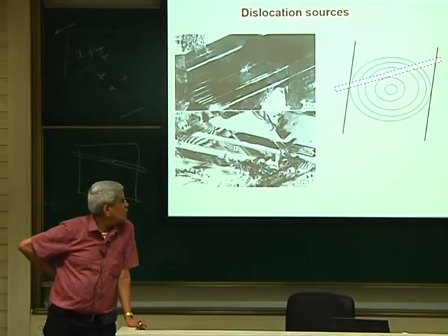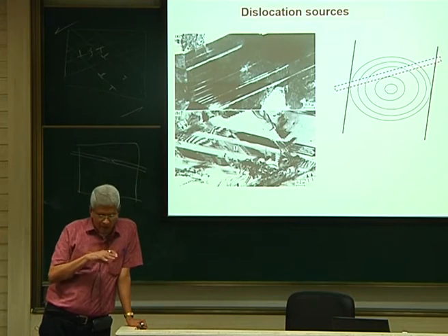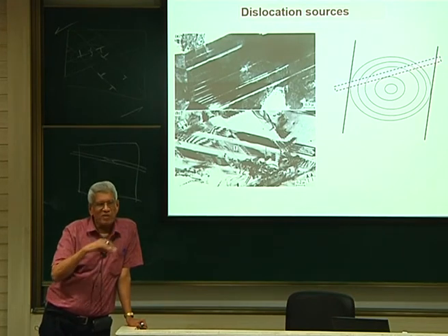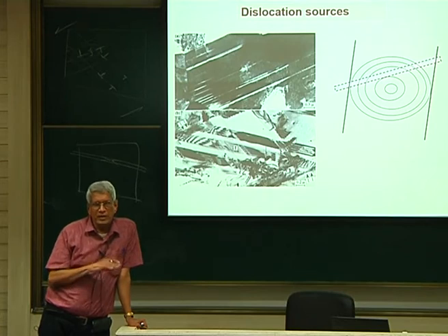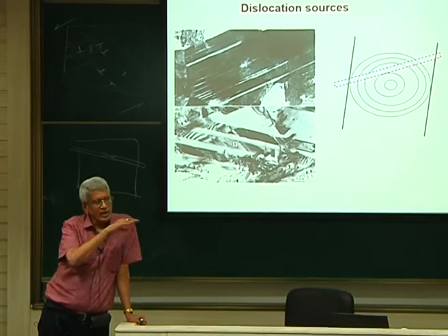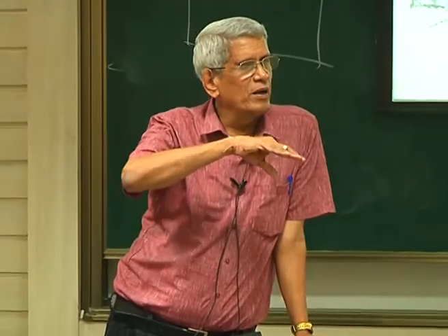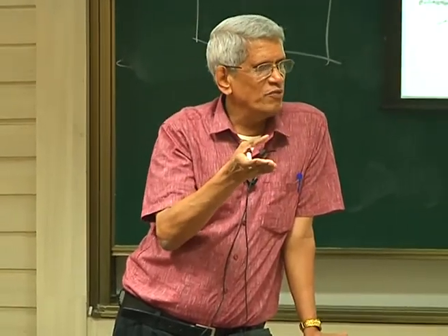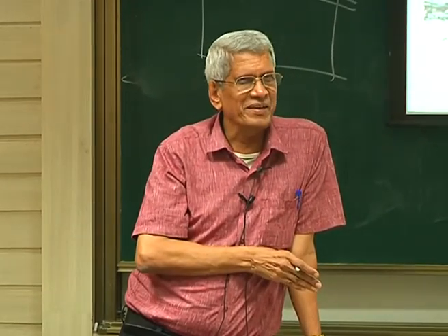So, in fact, when one wants to see a large area or large length of a dislocation within that foil, the best thing to do, one precaution which one has to take, is to cut the sample at 45 degrees with respect to the loading axis. So, if we slice the sample at 45 degrees with respect to the loading axis, what we know is that with respect to that axis, some of the grains, that angle corresponds to the maximum Schmid factor, correct?